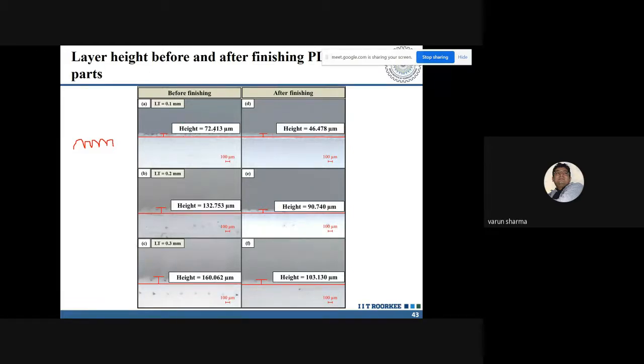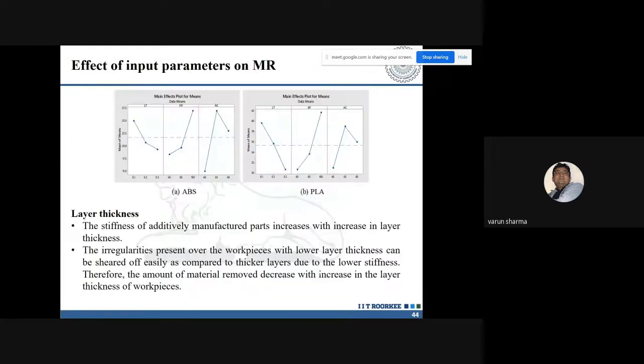Now as the material removal occurred, some portion of the domes was being eroded away with the abrasive particles. So we were able to reduce this particular height from 72 to 46 microns. For layer thickness 0.2, from 132 to 90 microns, and for 0.3, from 160 to 103 microns, we were able to reduce it for the PLA finishing. So if we look towards this particular